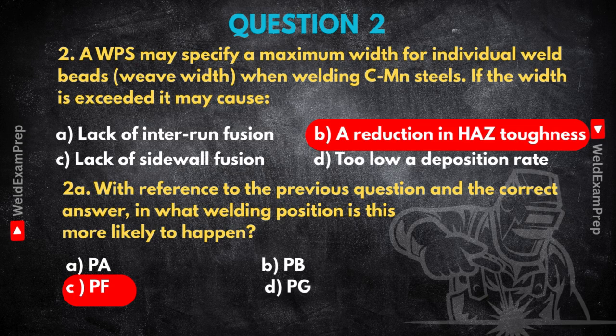Compare that to, say, PA flat or PB horizontal. Gravity is less of an issue or even helps. Control is usually easier without needing such wide weaves. And PG, vertical down, that's typically much faster travel, lower heat input per unit length generally. So while it has its own challenges, excessive weave width causing HAZ toughness problems is less common there than in vertical up. So yeah, for you as an inspector, knowing that vertical up is prone to this helps you focus your attention, to look closely at the weave consistency and be aware of the potential impact on the HAZ in those welds. It guides your inspection. That's really insightful. Knowing the why behind the position makes a huge difference.